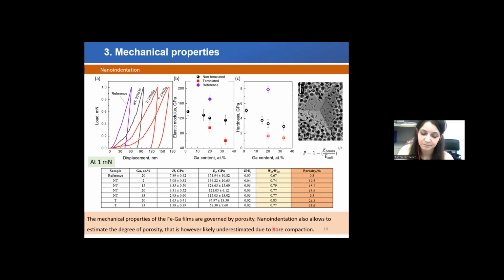Nevertheless, these numbers are likely to be underestimated because during the loading of the tip into the surface, there is some pore compaction happening. Actually, we can see it from this indentation imprint here in this image. Also, we can observe it from the shape of the load-displacement curves, especially for the highly porous samples. There is this flattening of the curve at the low loads that can be attributed to the pore collapse.